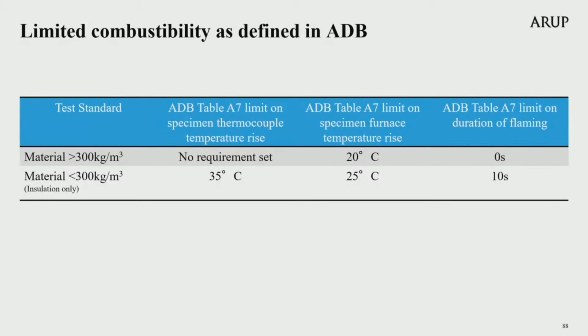The definition of a material of limited combustibility sets out not just temperature and flaming limits, but also makes a distinction regarding the density of the insulation material. If the material density is more than 300 kilograms per meter cubed, the limit on specimen furnace temperature rise is 20 degrees C, with 0 seconds of flaming to have been observed in the Part 11 test. If the material is of density less than 300 kilograms per meter cubed, the limits for observed flaming increase to a total of 10 seconds over the course of the whole test. The limit on specimen furnace temperature rise is slightly higher at 25 degrees Celsius, with an additional limit set on specimen thermocouple temperature rise of 35 degrees C.